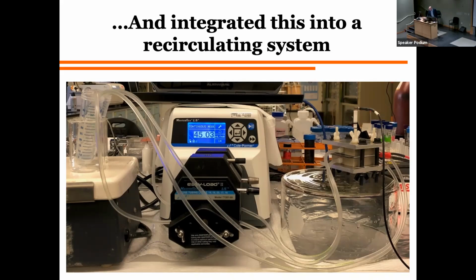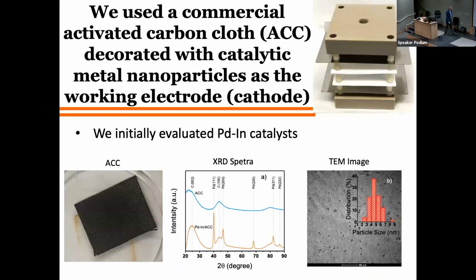And so, like I mentioned, for our cathode, we used an activated carbon cloth. And we said, well, let's decorate it with what we've been doing in conventional catalysts, this palladium and indium. And so here's the activated carbon cloth, just an XRD. It's got a little bit of signal from it. When we load the palladium, we get to see the spikes. We don't have any peaks for indium. I don't know if the loading was too low in that case. And then you can just look at TEM and see how the palladium is distributed on the surface and see that it's got fairly uniform size and is distributed pretty homogeneously.